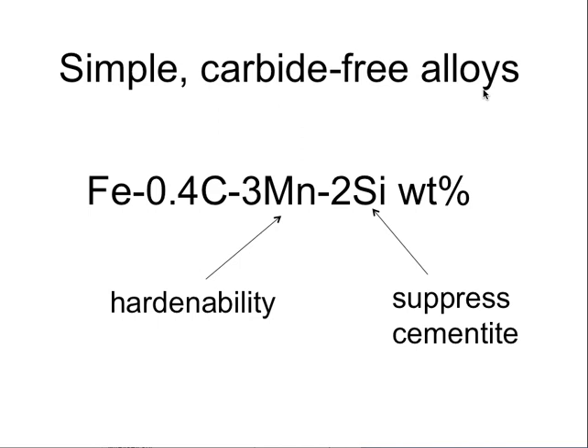It is a very simple steel — not normal, since a normal steel will contain 20 different alloying additions — but we want to prove a principle here. The silicon is added to suppress the cementite, the manganese to suppress the formation of high-temperature reconstructive transformations, and the carbon we need for strength. We are aiming for high-strength steels.